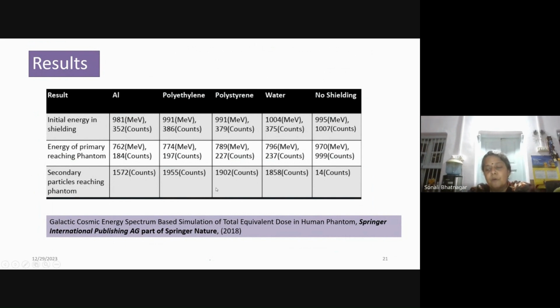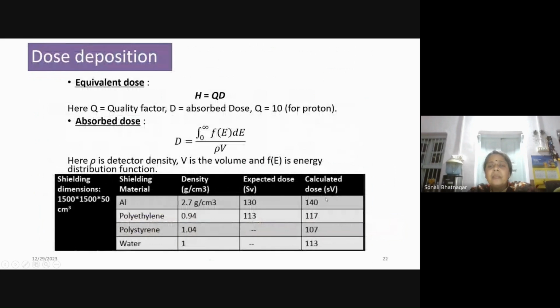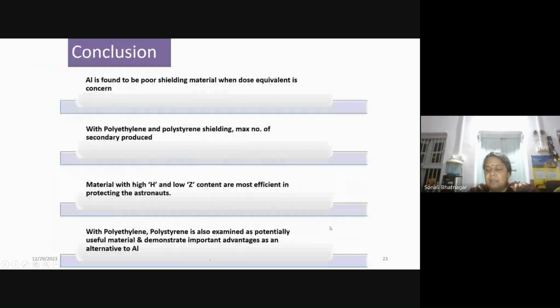And the more important factor was this, that the calculated dose was comparable in these two materials. So dose deposition was minimum in these two cases. This is exactly what we wanted. Of course, water is never used, so we were always looking at the comparison with aluminum, and so we got a very good result, and this was accepted as a publication.